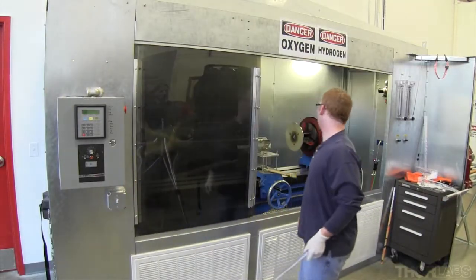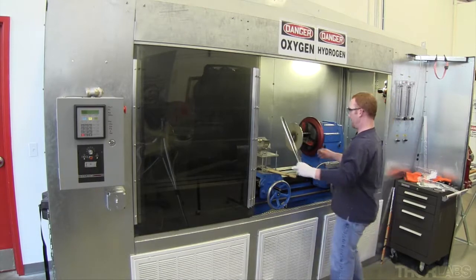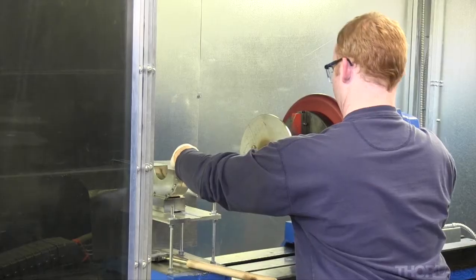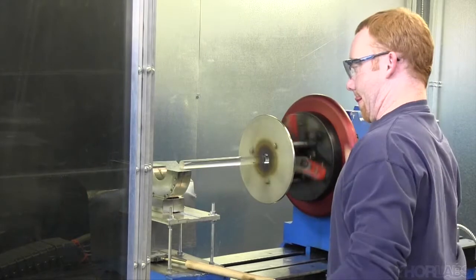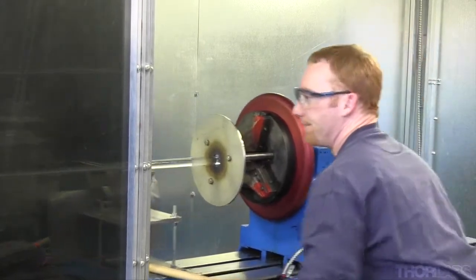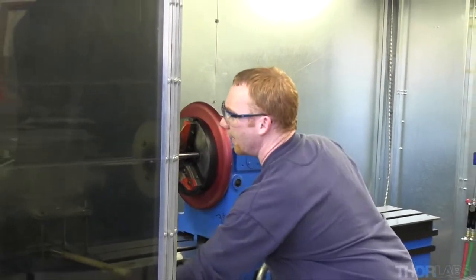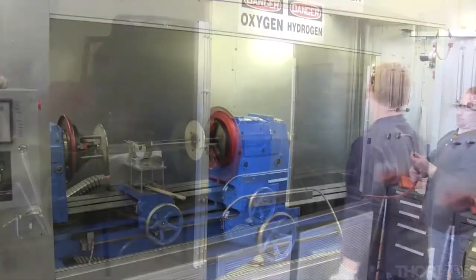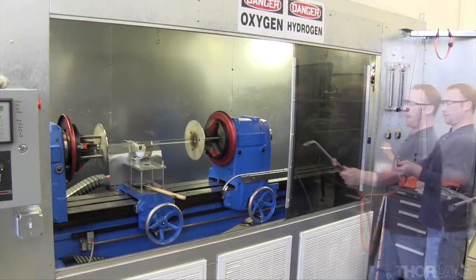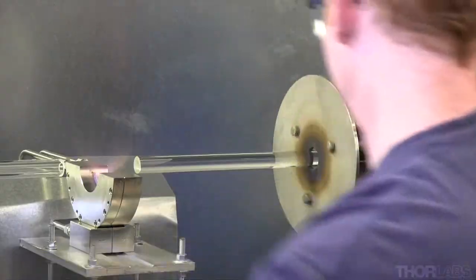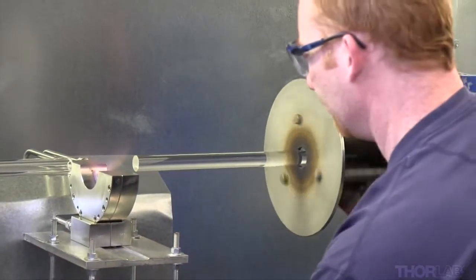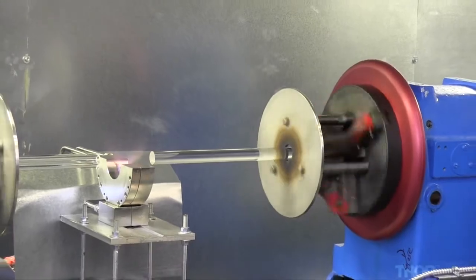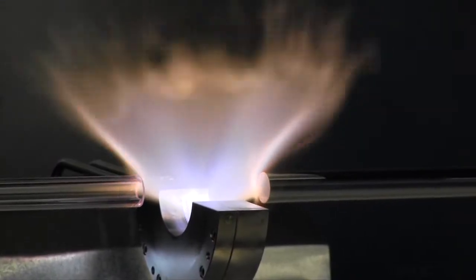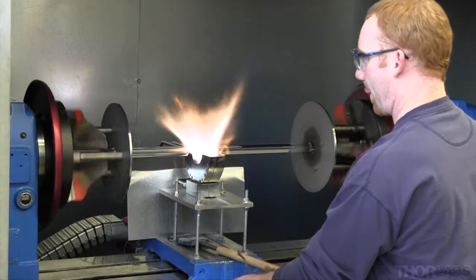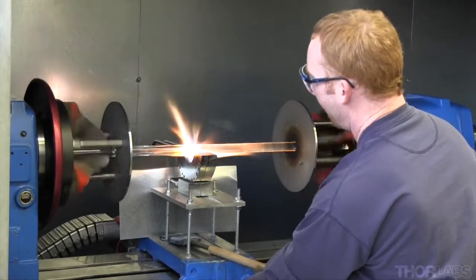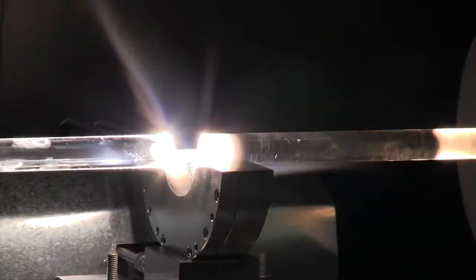The draw process begins by cleaning all surface contaminants from the silica preform. The internal structure of an optical fiber is already present in this 1-meter-long glass cylinder. A quartz handle is welded onto each end of the preform using an oxygen-hydrogen torch that heats the glass to 2,000 degrees Celsius. Eye protection is required to shield the engineer's eyes from the brightness of the torch.